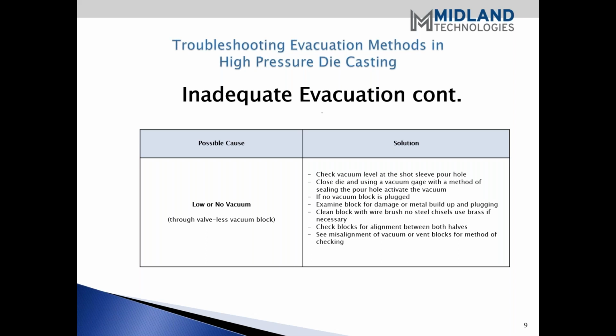We've had instances where die casters were saying they were getting buildup on their blocks. Well, this is the same as a die needs to be blown off, and release agent can be sprayed on the blocks themselves, and then a good blow off will help prevent the particles, which are all part of this particular process, from adhering to the teeth and possibly clogging up your vacuum system. And of course, as we mentioned before, you want to check the alignment between the blocks once you've determined that you're not pulling a vacuum, or at least the level that you may want.